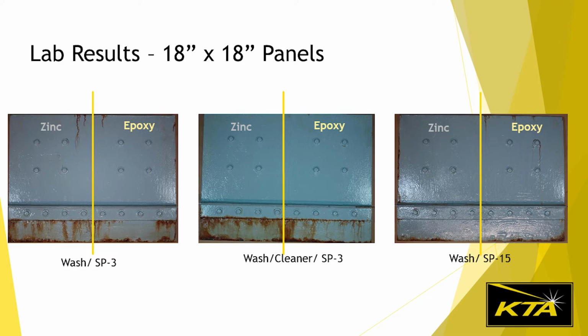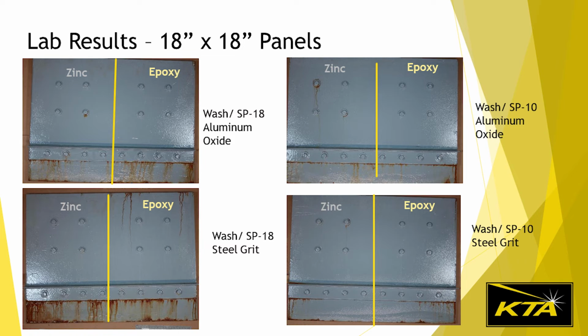The panels on this slide are the result after 40 cycles. So the corrosion, as you can see, is coming from the crevice, and no caulking was applied. For the SP3 clean panels, the epoxy is actually performing slightly better than the zinc, and SP15, they're pretty similar. Here are just a few more photos of how the zinc systems are performing against the epoxy systems. Panels on the left are SP18, panels on the right are SP10.